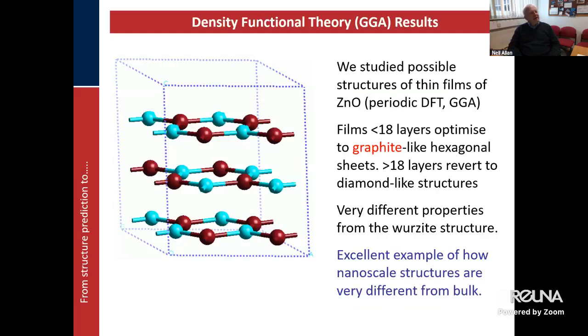And so we showed that for thin films, the structure, well, for a single structure, it would be a graphene-like layer, hexagonal type of layer. And that was actually the lowest energy for films of about up to 18 layers. And of course, just like graphite is different from diamond, so these films have very different properties from that of the bulk zinc oxide. They're photocatalysts, apart from other things. So altogether, it's an excellent example of how nanoscale structures are very different from the bulk.